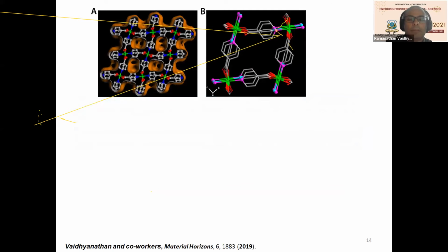So the magnesium isonicotinate structure is shown here. The green balls are the magnesium, okay? And it is connected by the isonicotinate ligand. One end is connecting through the pyridyl group, another end through the carboxylate group. The red balls are the oxygen atoms of the carboxylate. The blue balls are the nitrogen atom of the pyridyl group. The gray balls are the carbon of the benzene ring to which these groups are attached. And the green balls are the magnesium centers, okay? So now this has a nice three-dimensional structure, but with one-dimensional pores.